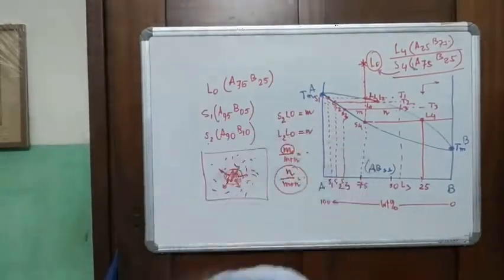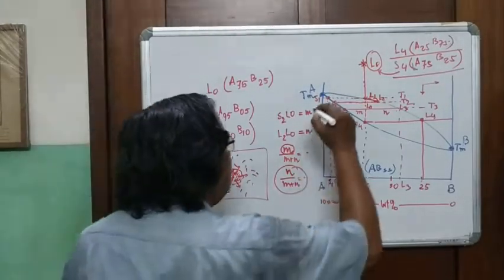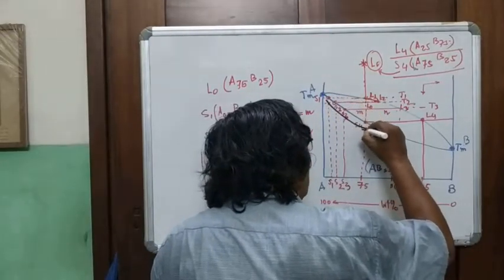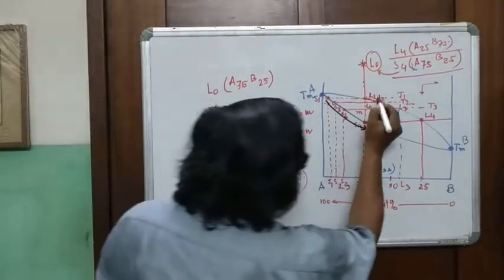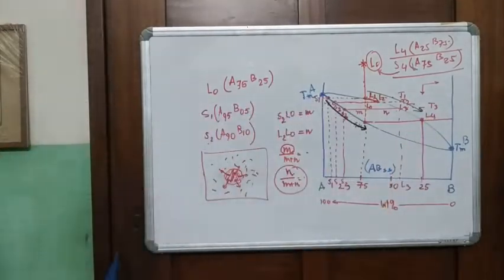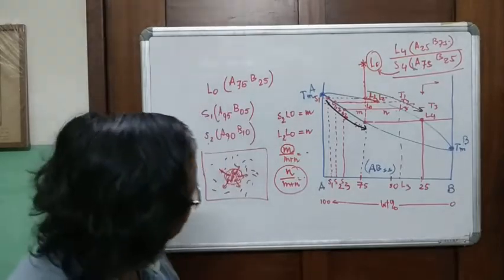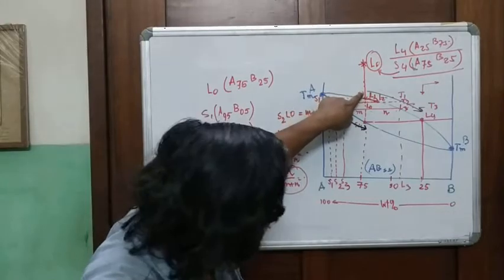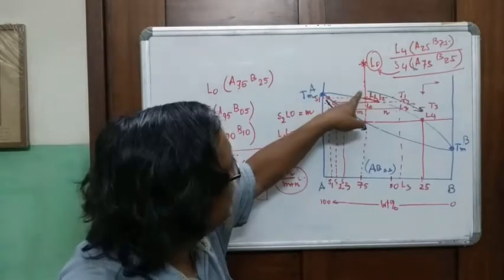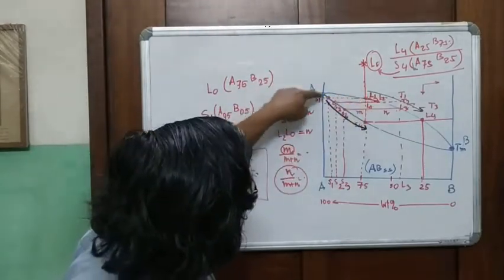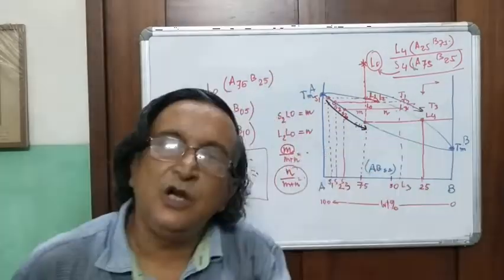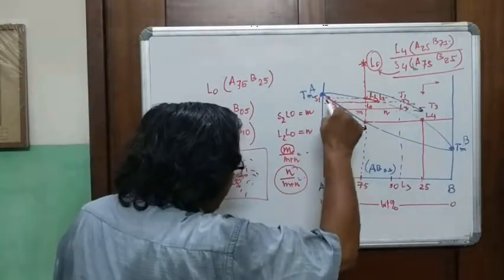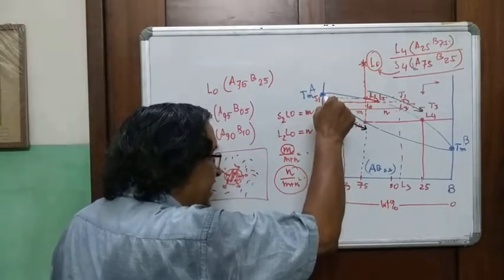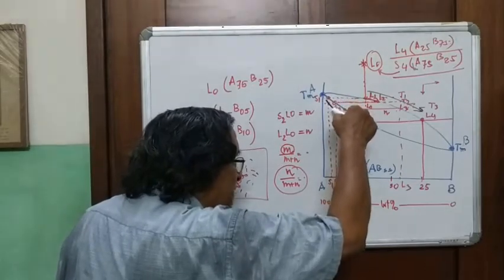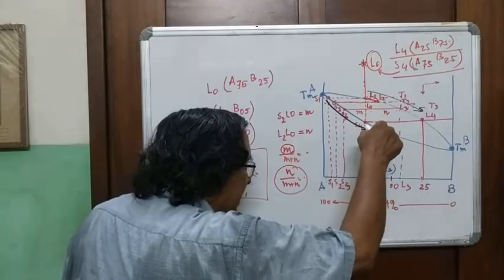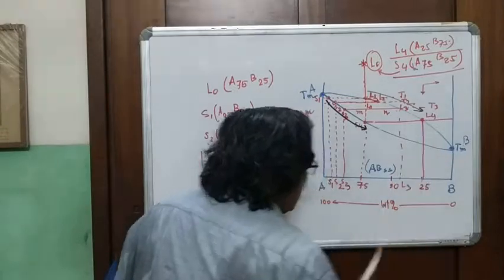As you move down, as you crystallize, the solid composition moves from S1 to S4. This is how the solid composition moves, and the liquid composition moves from here to here. The important part to discuss here is that the liquid composition was initially here, and then it moved towards this. That means, to start with, the liquid composition was richer in the higher temperature component, but ended up being lower. Similarly, if you take the solid, it started with very enriched components, enriched in A, but through interaction with the melt, the crystal composition continuously changed till it reached the same composition as the initial melt when the last drop of liquid was exhausted.